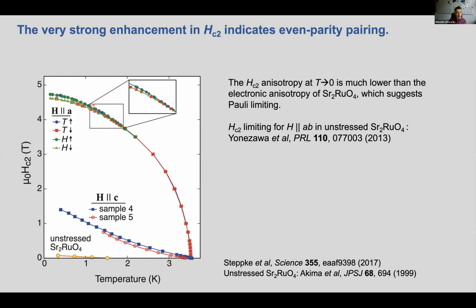Instead, we only see 4.5 Tesla, and we also see a very clearly first order superconducting transition. We see clear hysteresis between increasing and decreasing field sweeps. So this is an indication of Pauli limiting, and generally that occurs when the pairing is spin singlet and when the orbital order is even parity.